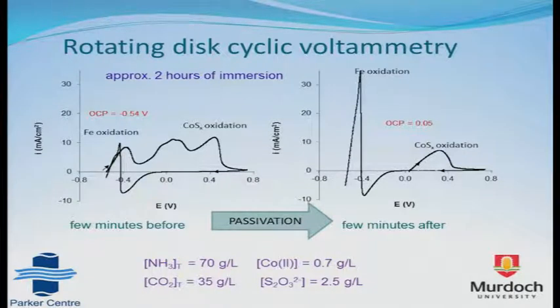So it's a different case to the case of copper, where iron passivates and the copper is then redissolved. In this case, the cobalt sulfide remains on the surface. Before passivation, it seems to suppress the dissolution of iron, and after passivation, it is still on the surface. So it's interesting to know how long it takes to redissolve, because if it doesn't redissolve fast enough, that will account for some losses of cobalt.